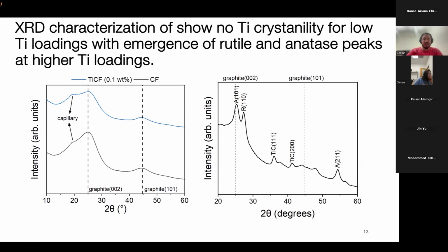So on the left, you can see the XRD for the carbon nanoflower without any titanium doping. And then the 0.1% titanium on carbon nanoflower that has titanium doping, but you can see that there are no titanium peaks, showing that there's no to very little crystallinity in the titanium that is in the nanoflower. And if you increase the titanium loading to 0.7, you can see that you start seeing some peaks for anatase and rutile and some other crystalline titanium forms, which indicates that there are titanium nanoparticles forming and agglomerating on the surface of these nanoparticles.